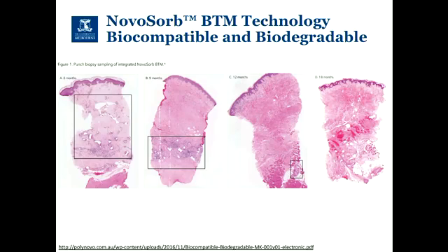But these are some histology slides of the scaffold that has been implanted. If we're looking at histology, pink is tissue, purple are cells. This one is 6 months after it's been implanted. You saw the scaffold is a porous material that cells are infiltrating. So you might see all of the holes where the tissue hasn't integrated and infiltrated yet. And you still see a lot of purple in the 6 month one, so there's a lot of cell infiltration. Look also at how big the area of the scaffold is.